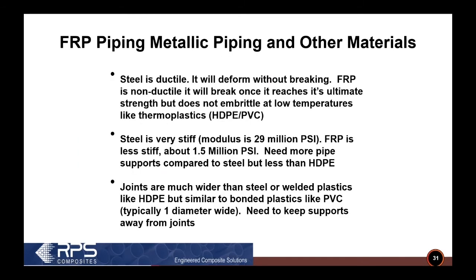So how does FRP compare to metallic piping and other materials? Well, steel is ductile and it will deform before it breaks. FRP is not ductile. It'll break once it reaches its ultimate strength. However, it doesn't get brittle at low temperatures like thermoplastics, PVC or HDPE. Steel is very stiff, has a modulus of 29 million. FRP is much less, around 1.5 million. And that means you need more pipe supports in an FRP system than you would in a steel system, but less than HDPE. The joints are much wider than steel, where you can just weld the two pieces together. In FRP, you either have to bond the pieces together or laminate the two pieces together. So typically the joints are about a diameter wide.